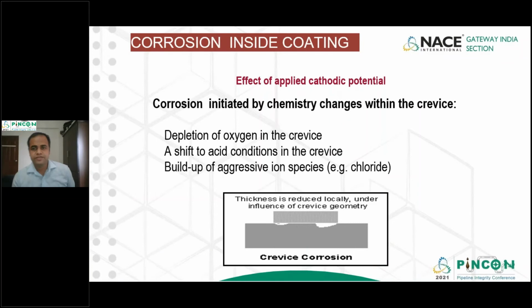Now, when you see the chemistry changes inside the crevice, basically the depletion of oxygen in the crevice leads to an acidic condition in the crevice, and further to that, it tends to create aggressive ionic species, which form a layer of deposit on the crevice. And further, you can say that the movement of ions from the outside environment to the crevice won't happen as fast as it used to be because of this formation of aggressive ions.